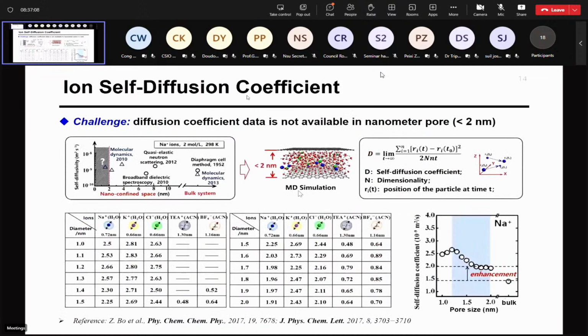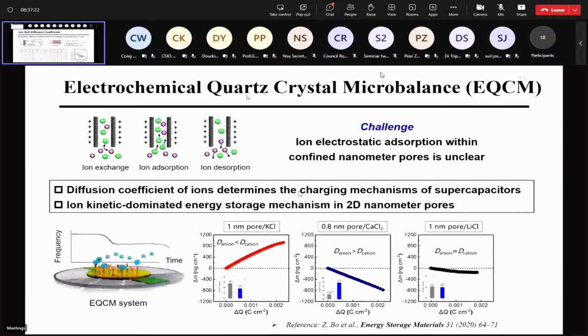We also calculated the ion self-diffusion coefficient in the nano-confined spaces, since it's very important to determine the electrolyte conductivity, and also the performance in supercapacitor applications. We use the EQCM, a microscopic measurement technology, to determine the mode in the nano-confined spaces. Basically, it has three modes: ion exchange, ion adsorption, and ion desorption. So we found the ionic dominated energy storage mechanism in two-dimensional nanometer pores.